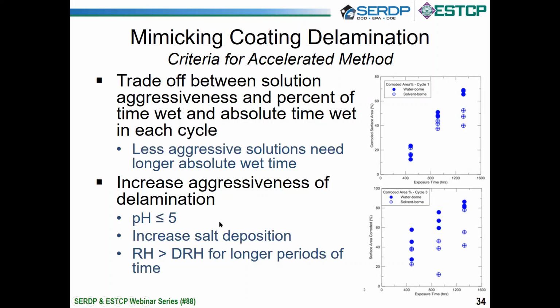So what drives aggressiveness of the solution is the pH. I showed that in a number of cases. Obviously it increases salt deposition because it increases the surface area and taxes inhibitors more. And then the other thing is the amount of time above the deliquescence point, as I demonstrated here.